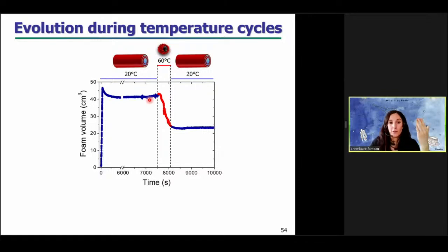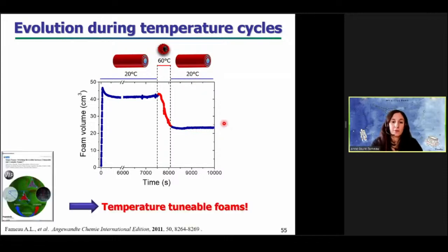But by increasing the temperature to 60 degrees, tubes transit into spherical micelles inside the foam, and we observe very fast foam destabilization. But remarkably, by decreasing back the temperature to 20 degrees, tubes are reformed inside the foam, and we observe that the foam volume remains constant again with time. So with this simple system of fatty acids, we obtained the first temperature tunable foams 10 years ago.